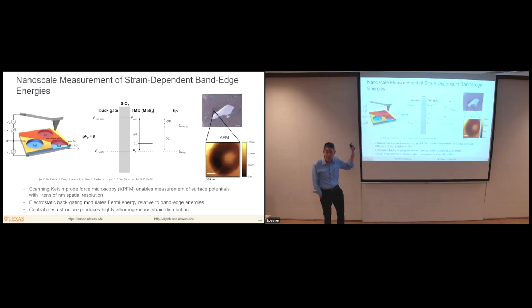So I'll talk first about how we have looked at measuring nanoscale strain distributions. And we do this by using a scan probe technique known as Kelvin probe force microscopy. Okay, and the basic idea is shown in this slide here. So this is an AFM-based technique, and the sample structures that we create consist of essentially a bottom metal contact here into which we have etched these cavities in an underlying SiO2 layer. And then we have these submicron scale mesas over here. And then we transfer monolayers of TMD materials, specifically MoS2 in this case, onto that surface. And so this mesa here gives us a geometry that is similar to what is used for single photon emission. All right. And then in addition, we have a backgate electrical contact to the underlying silicon substrate.